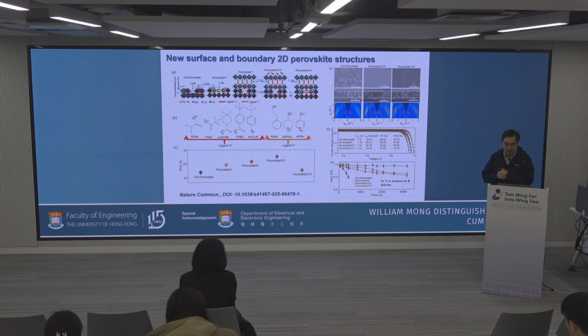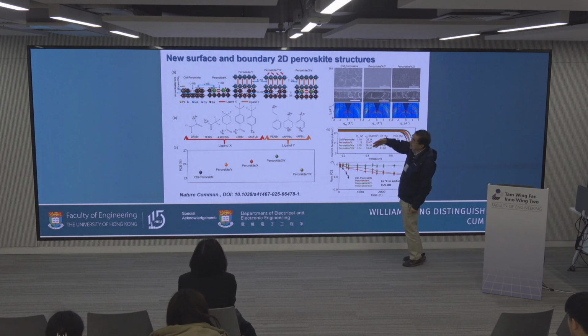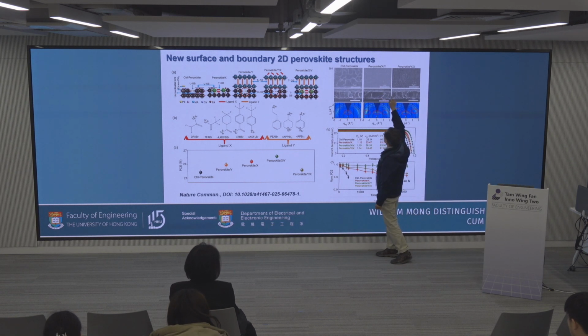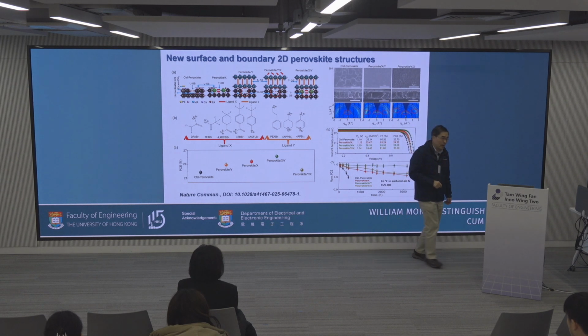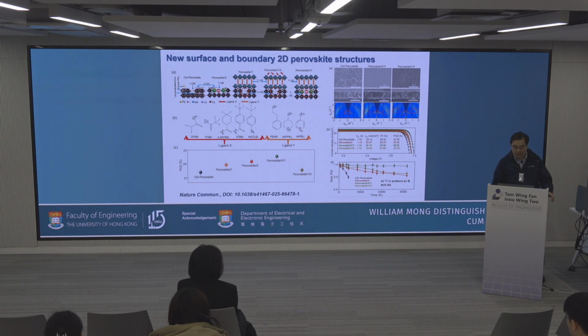So next, we remember that we talked about we have surface, we have boundaries. Can we do something so that we do not just look after the surface, we also look after the boundary? So what we do is that we try to find some ligands which can add the modification, which can help us to address both the boundary issue, that is the boundary, right, between the grains. That is the surface. Those two regions are where we have a lot of defects degrading the performance.